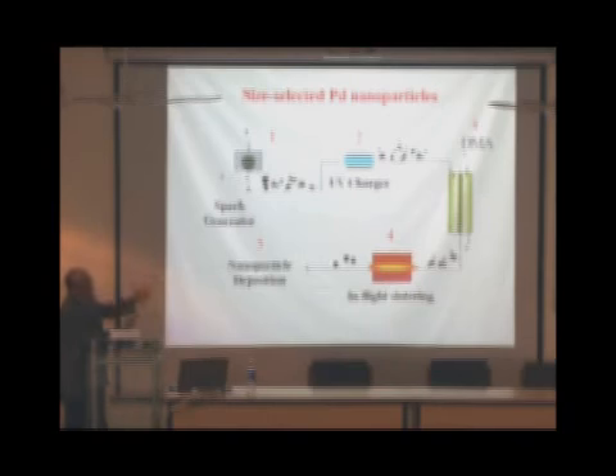Let's say we are making palladium nanoparticles. We have two rods of palladium, and there is an arc between them, and because of that the palladium goes to the vapor phase, and the carrier gas A and B takes these vapors along this line. As they go, these atoms collide with each other and form agglomerates. As shown here, these agglomerates are of different sizes. They have arbitrary shape because they are formed due to the statistical mechanism of collision of these atoms, and then they form small particles. These small particles will again collide and form agglomerates.